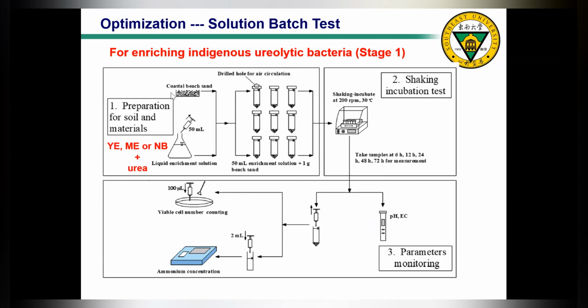For the test, we mixed 1 gram of beach sand with the enrichment solution. Here we have 3 types of enrichment solution: YE is yeast extract, ME is meat extract, and NB is nutrient broth based ureolytic enrichment solution, because in this solution we also have urea inside. When they are mixed, they are subject to shaking incubation for different periods, and then the samples are subject to pH, electrical conductivity, and ammonia concentration measurements. Also, we performed the viable cell number counting.